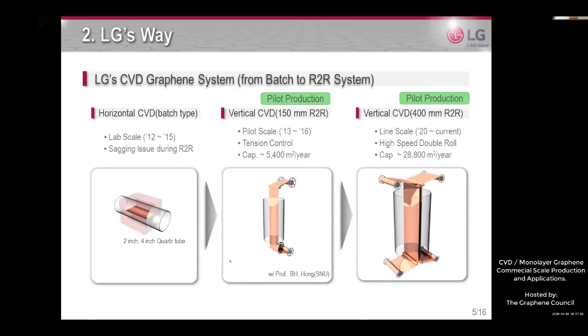The first generation is a lab scale system and is impossible for mass production. So we considered and developed the mass production system. The second generation is a vertical roll-to-roll CVD system with 150 millimeter width. The quality, reliability, reproducibility and productivity were secured, and it is operating for mass production from last year. It's a pilot scale stage, and its capacity is about 5,400 square meters per year.